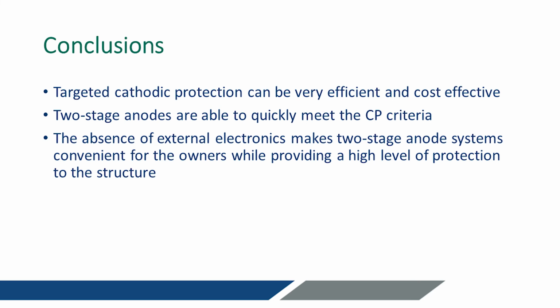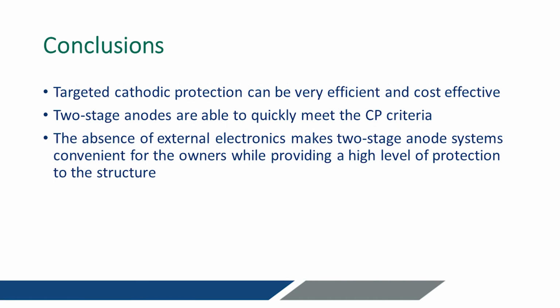So in conclusion, targeted cathodic protection can be very efficient and cost effective. So we're just applying the CP where the risk for corrosion is high so that we can prevent corrosion and extend the service life of that structure. The two-stage anodes are very nice because we can get benefits of both a galvanic and an impressed current system in one. We don't have external electronics that could break down or be destroyed, but we also have a higher capacity in the anode, so we reach passivation much quicker than we would with a galvanic anode.